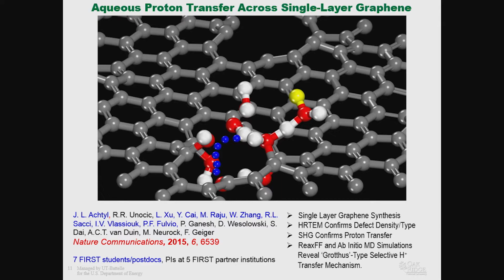We have 5 of our Oak Ridge, and partner institutions involved in the research. 7 of our first center students and postdocs are among the lead authors. This work combines single-layer graphene synthesis, very large graphene sheets which could be synthesized and transferred to a substrate, high-resolution TEM studies of the defect densities and structures, second harmonic generation studies to establish the proton transport kinetics, and both reactive force field and ab initio MD simulations to elucidate the reaction mechanism.